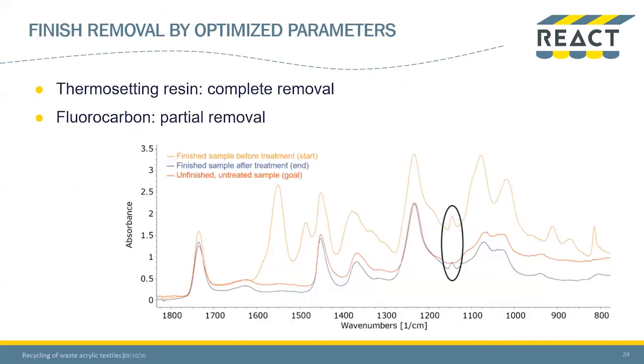And these optimized parameters resulted in the end in a complete removal of the thermosetting resin and a partial removal of the fluorocarbons via a one-step process, which was optimized at Ghent University. So although the fluorocarbons were only partially removed, since we noticed traces still present in the infrared spectra, the fabrics could be wetted again after this process.